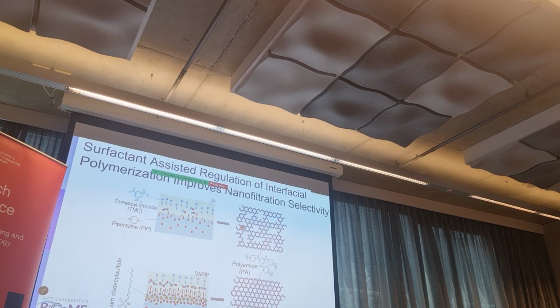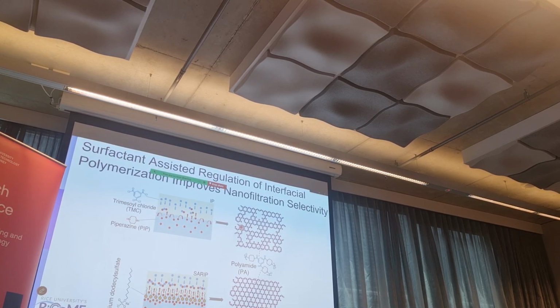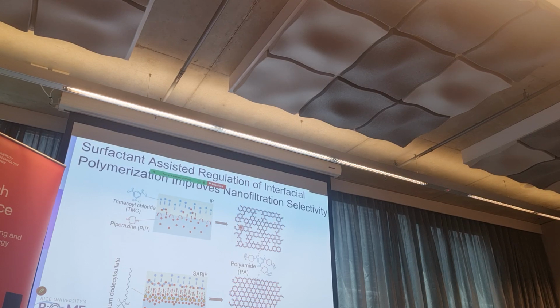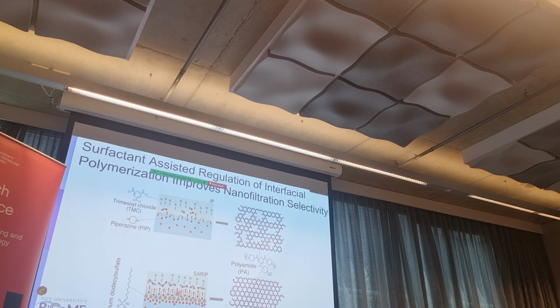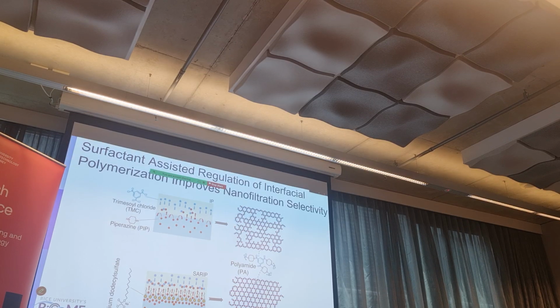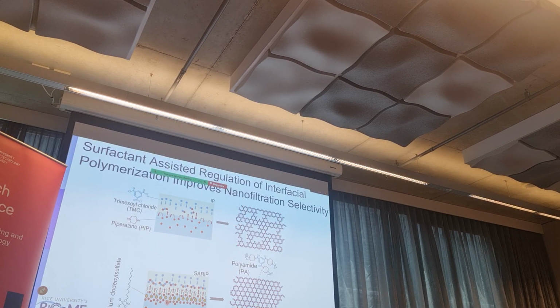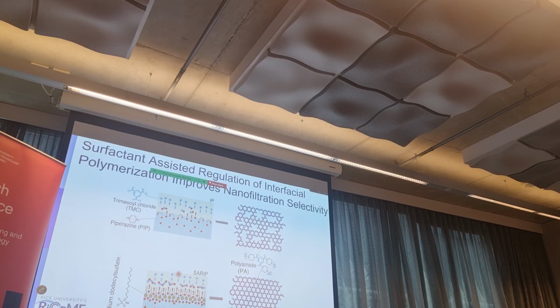So I'll show you some work that was done by Liang et al. I was part of the team, with Xiong and Lin. For this IP, they used the same interfacial polymerization, but added sodium dodecyl sulfate to the aqueous phase. When you do interfacial polymerization, you have an aqueous phase and an organic phase.